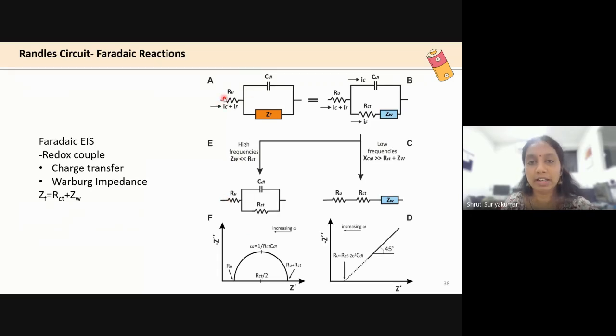You have current coming in. That current is going to split into two terms. One is for the double layer charging, and one is for the Faraday. And when it is coming for the Faraday, it could work in two ways. At lower frequencies, as I said earlier, it's not going to have a capacitive contribution, and it is only going to flow through this circuit element, which is going to be the RU, RCT, and ZW. This is what you will be getting when you're looking at lower frequencies.